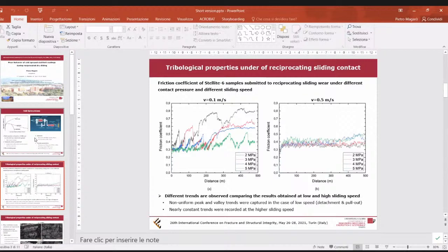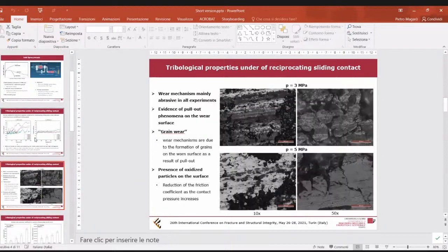speed and contact pressure. In fact, the first result is the difference in the evolution of the dynamic friction coefficient as a function of the sliding speed. At low speed, 0.1 meter per second, we can see big fluctuations in the friction coefficient, and an almost constant trend is observable at 0.5 meter per second. This phenomenon can be related to the different damage mechanisms observed on the wear surface of the samples at the end of the test.